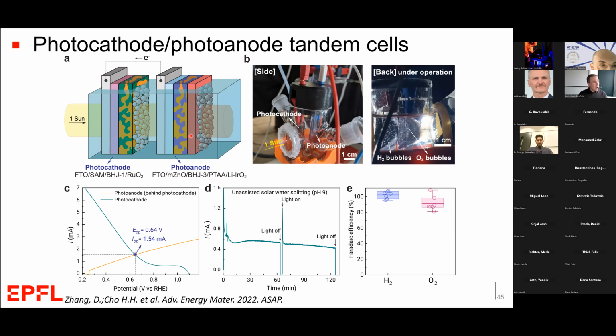But after that, we were able to demonstrate unassisted overall water splitting at a solar to hydrogen conversion efficiency of only about 0.5%. So a very modest demonstration here, but the first time that this was ever done with organic semiconductors, both in the photocathode and the photoanode. So I think I'm probably running out of time.